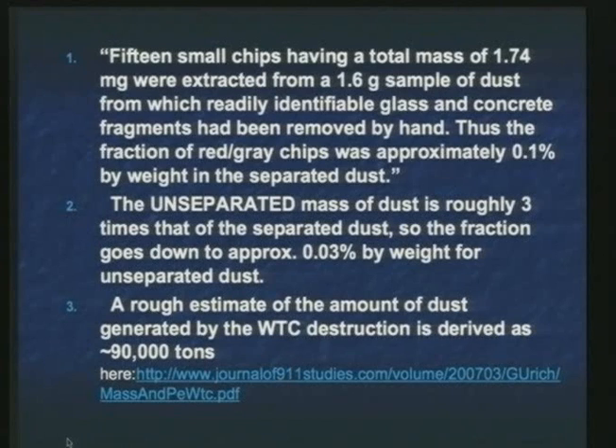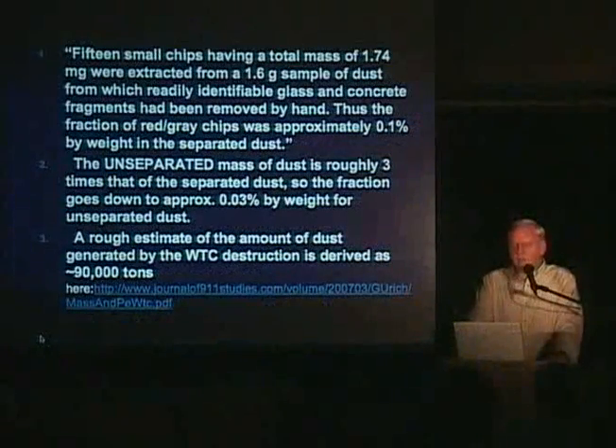How much material was in the dust? I want to go through this argument quickly. We report in the paper, the first paragraph is a quote from the paper: 15 small chips having a mass of 1.74 milligrams, extracted from 1.6 grams of dust from which readily identifiable glass and concrete fragments had been removed by hand. The fraction then of red-gray chips was approximately 0.1% by weight in the separated dust. The unseparated dust is about 3 times that.